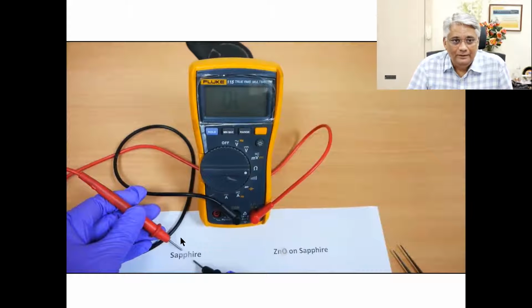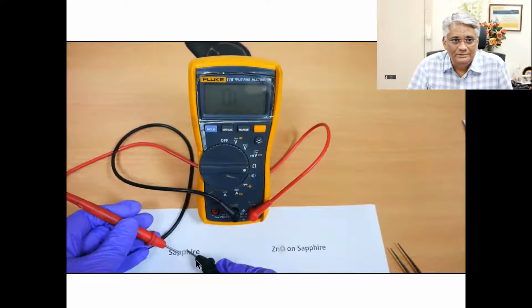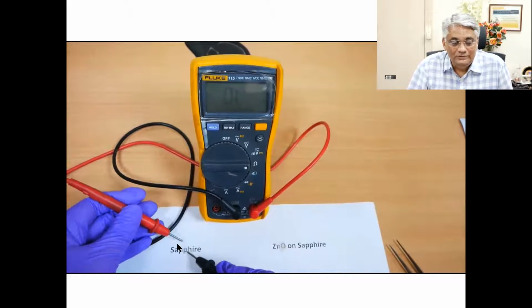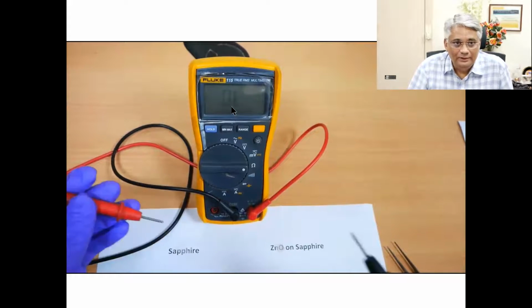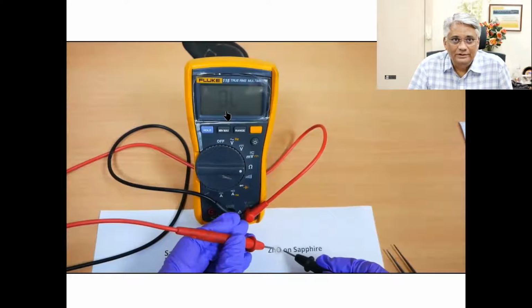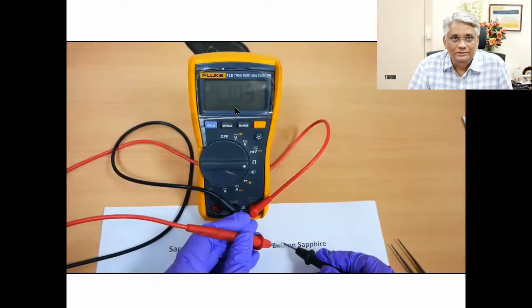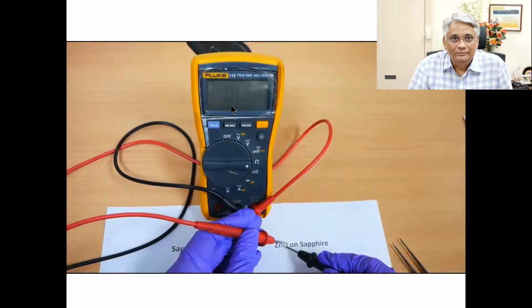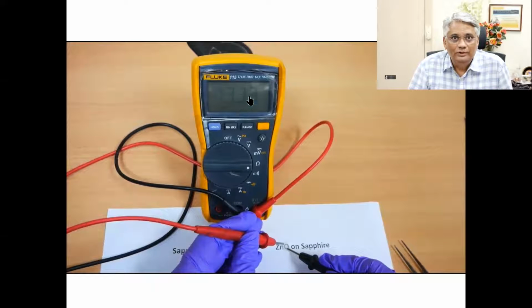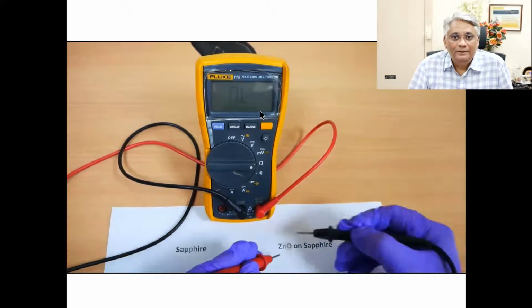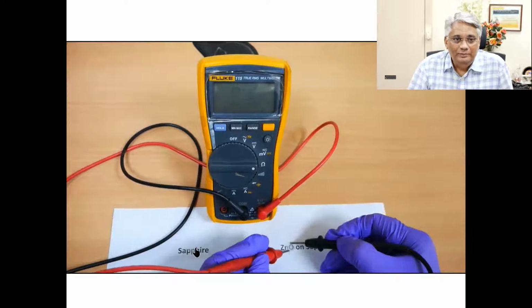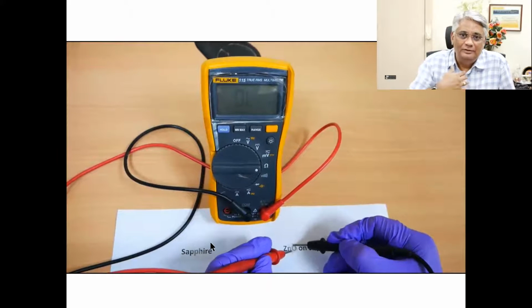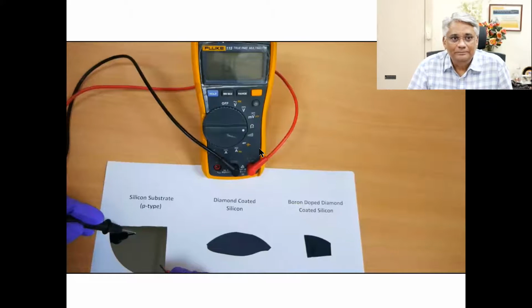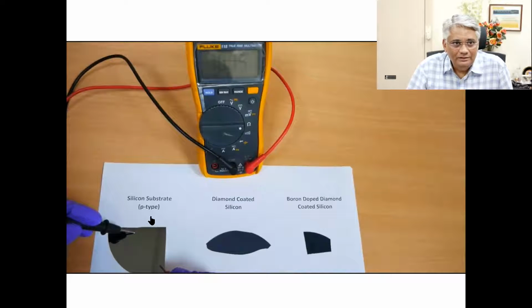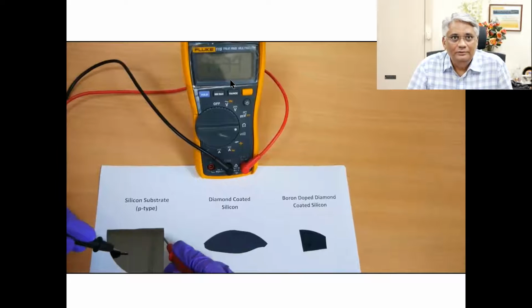This is sapphire. I was talking about it yesterday. Alpha alumina is sapphire. It's transparent, but it is insulating. It is made of alumina. But this is zinc oxide on sapphire. Okay, now you see that. It's about 14 kilo ohms there. You see, from a completely overloaded state, that means resistivity in giga ohms, the resistance changes by several orders, right? Now, this is a silicon substrate, P-type. You see 15 ohms there.